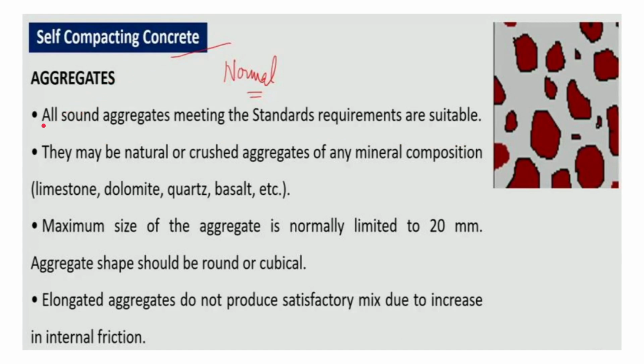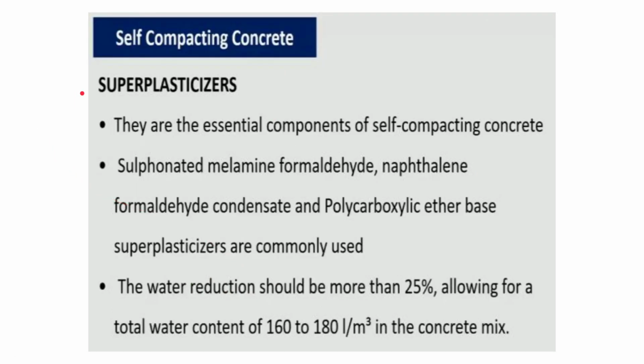Now let us go to the aggregate portion. All sound aggregates meeting the standard requirements are suitable for SCC. They may be natural or crushed aggregates of any mineral composition: limestone, dolomite, quartz, basalt, etc. The maximum size of the aggregate is normally limited to 20 millimeters, and the aggregate shape should be round or cubical. These factors need to be kept in mind for use in SCC. Elongated aggregates do not produce a satisfactory mix due to increased internal friction, which may result in segregation or improper flow. So they need to be avoided, and we can go for round or cubical ones. That is basically about aggregates.